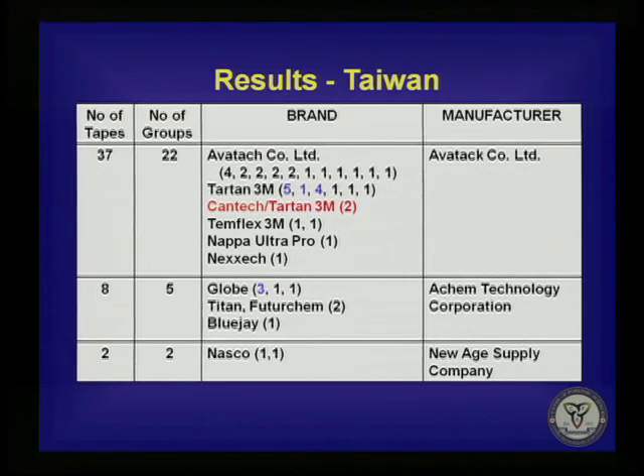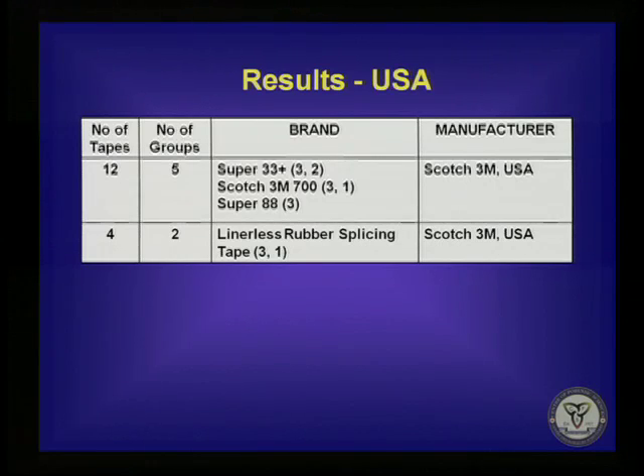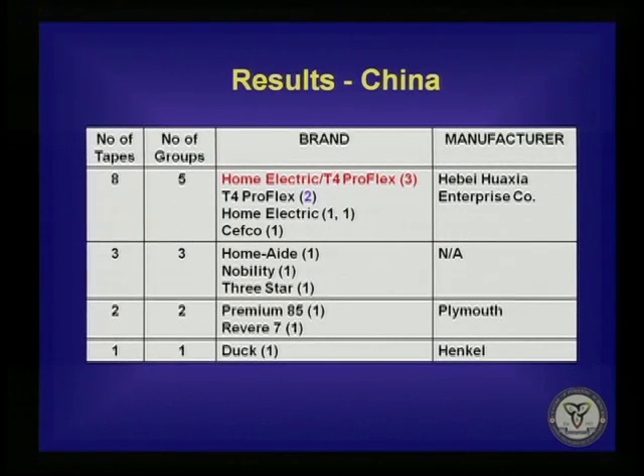Cantech, one group that had Cantech and Tartan 3M tapes, which we were not able to discriminate from each other. Then Achem Technology Corporation, we were able to divide those 8 tapes into 5 groups, and we were able to distinguish the tapes from New Age Supply Company. From the tapes manufactured in the USA, the 12 PVC tapes were broken down into 5 groups. We were able to distinguish some of the same brands, and then the 4 tapes that had the rubber backing, we were able to break down into 2 groups. And our last